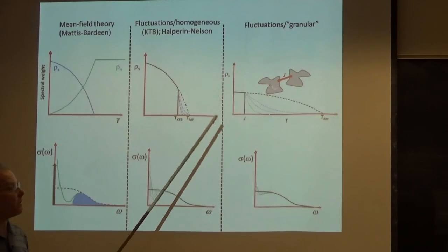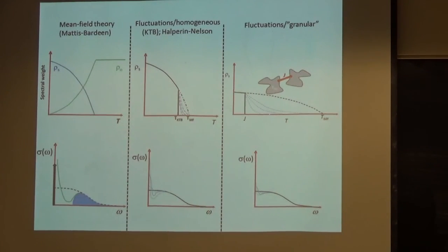So experimentally in a laboratory, this is what was done in the case of granular superconductors by making indium oxide films and varying the amount of oxygen as you evaporate the indium. You can continuously tune this J. And you should see that you get one characteristic temperature, which is the T_c of the indium, which doesn't change, and the other characteristic temperature, which is J, which you can drive all the way and ultimately go to the superconductor-insulator phase transition by completely destroying superconductivity.